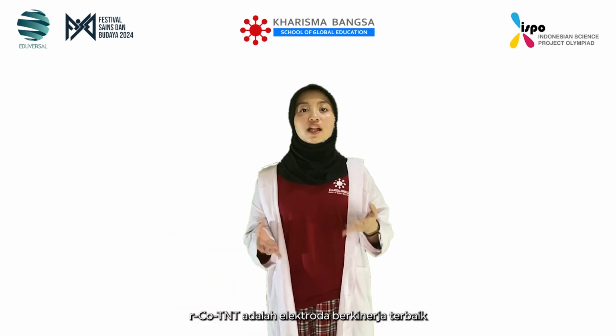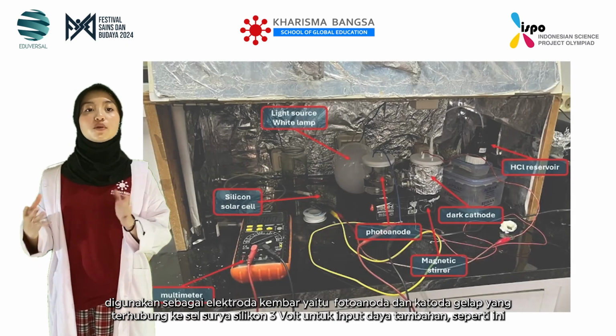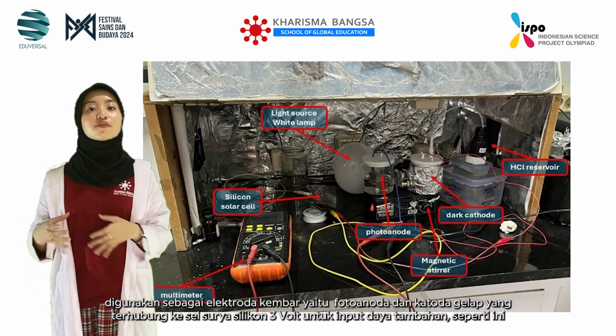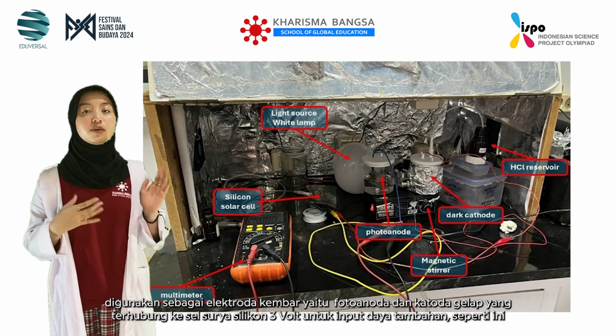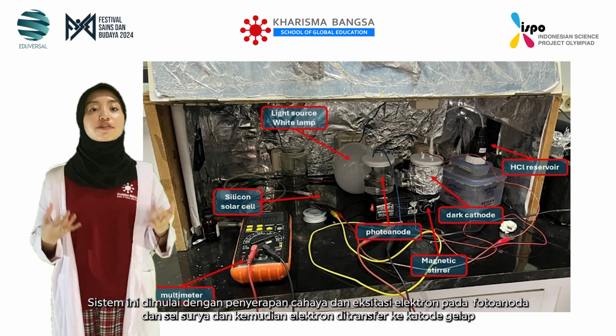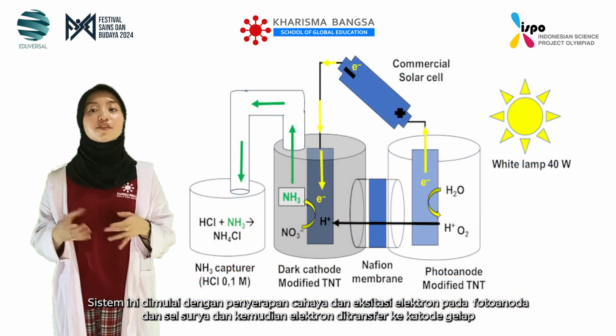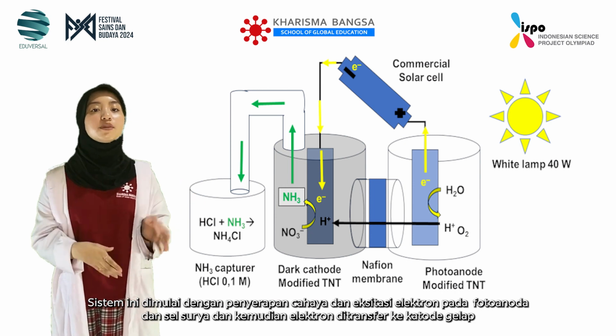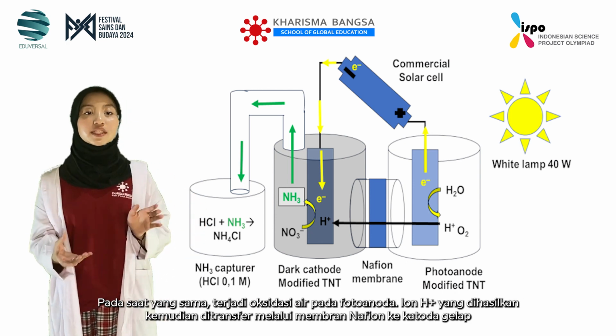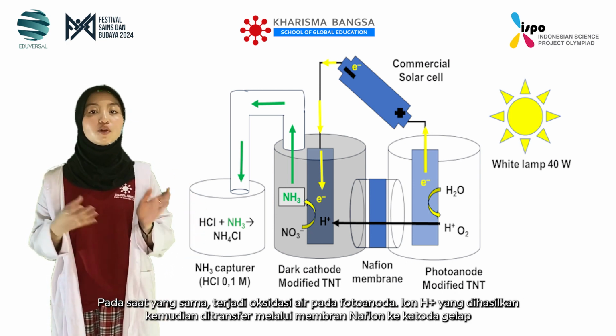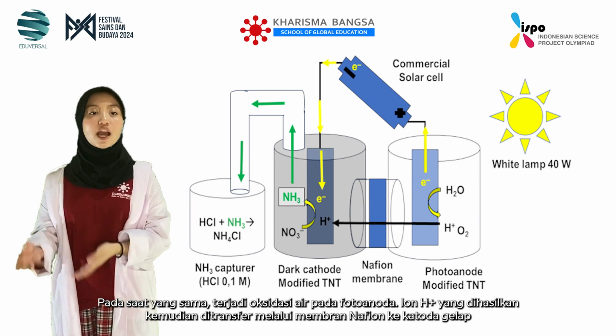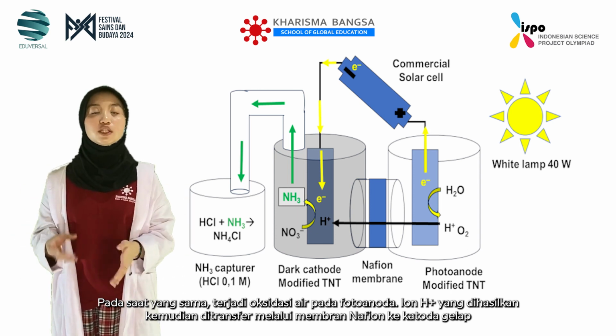RCo-TNT, the best performing electrode, was utilized as a twin photoanode and a dark cathode, connected to a commercial 3-volt silicon solar cell for additional power input like this. The system begins with light absorption and electron excitation at the photoanode and solar cell, which then will be transferred to the dark cathode. Simultaneously, the water is oxidized at the photoanode. The generated H+ ion is then transferred through the Nafion membrane to the dark cathode.